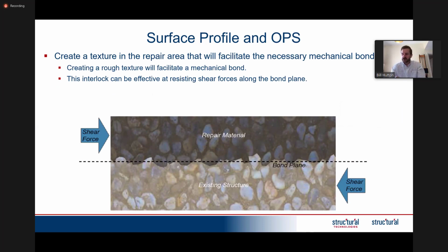In terms of surface profile, what we're looking for in a concrete repair is monolithic composite action. To get that monolithic composite action, we need to make sure we have a roughened surface on the native concrete. So we would chip and provide typically a 6 to 8 millimeter amplitude. We also want to provide an open pore substrate. As we said before, concrete is like a sponge. It has all these pores. So we need to make sure those pores are open so that when your repair material comes in, it's accepted by the native concrete.